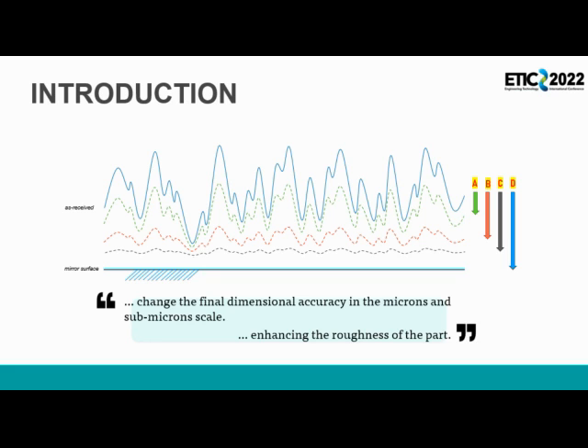Assuming this is a material surface profile, when this surface is polished with process A, for example sanding, the profile of the surface will change. Then it is followed by process B, for example grinding. Then process C, which is polished with lapping cloth with 3 micron diamond suspension, and finished with process D, which is a 1 micron colloidal silica suspension. You can get a mirror-like surface.